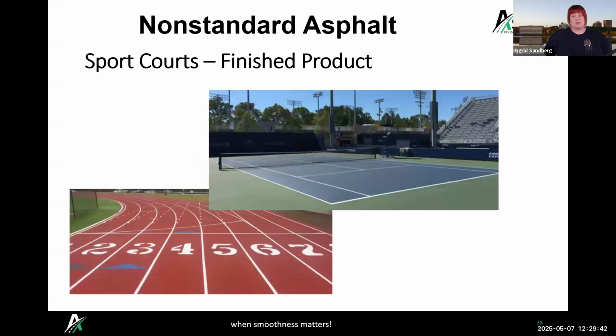So that goes into, we got a question about opinions on winterization, dewinterization of posts on the court. And I would say that anything that you can do to prevent water from getting in around that post over the winter and freezing and expanding is going to be helpful. Do you have any other comments there? A lot of the posts, especially on a tennis court, probably the best thing that you can do is instead of cementing the post down in there, you put a post sleeve and then the post can be removed and capped off, then that sleeve can be capped off during the winter and things like that.